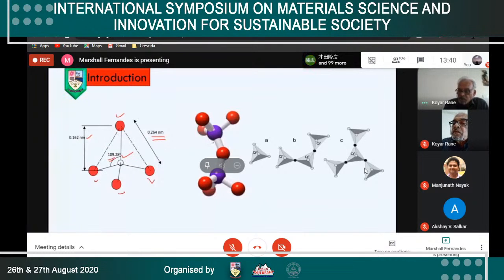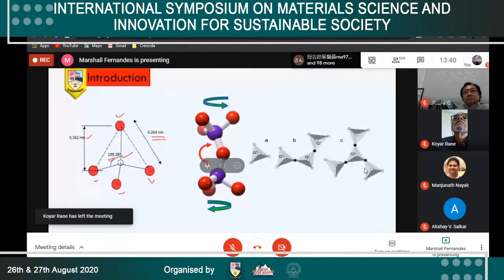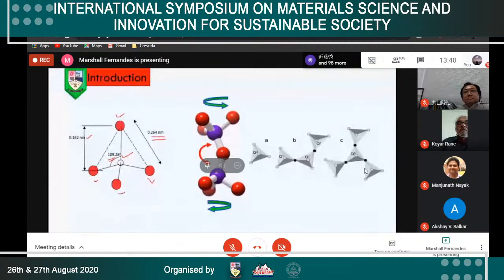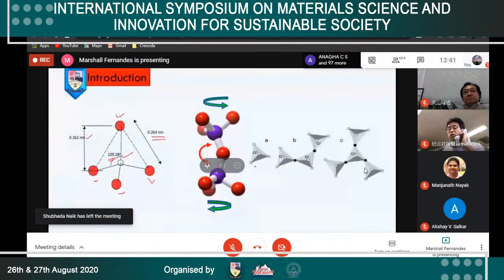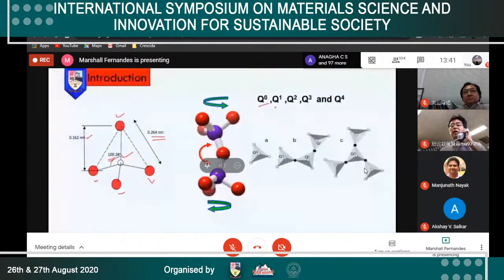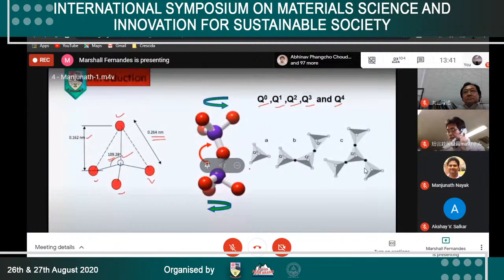The disorder in the silicate glasses is due to the rotation and bending between the connected tetrahedral units in an irregular manner throughout the sample. These major defects occur due to the rapid quenching of the samples from high temperature to room temperature. Next up here, we have similar silicon tetrahedra with different connectivities. I'm going to repeatedly use the terms Q0, Q1, Q2, Q3, and Q4 while discussing the Raman data. And for those of you who don't know what it stands for, let me just give you a very brief insight into it.